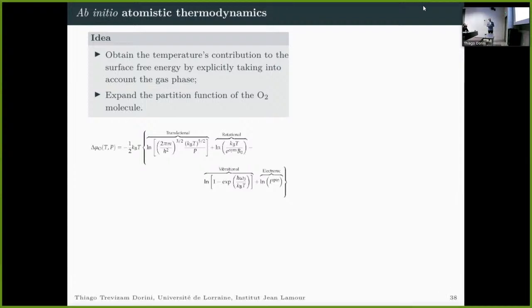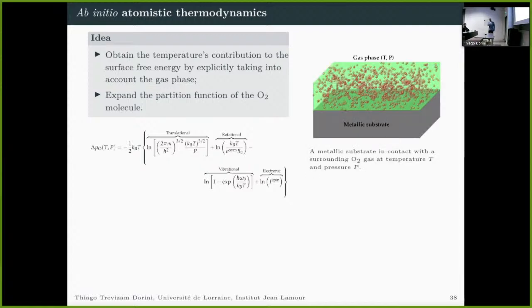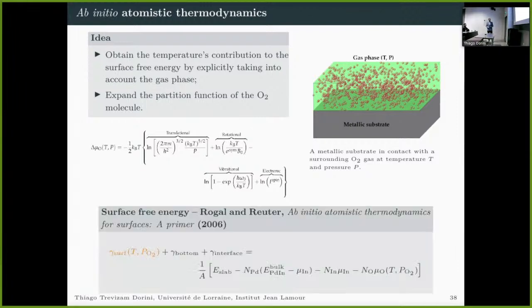In this methodology we use, we obtain the temperature contribution by taking into account explicitly the gas phase. So in this case, we expand the partition function of the oxygen molecule in terms of the translational, rotational, vibrational, and electronic features. And here we have a model of this system. So we have our metallic substrates and the gas phase here. And also we have on top a reservoir of oxygen molecules in contact with this system.